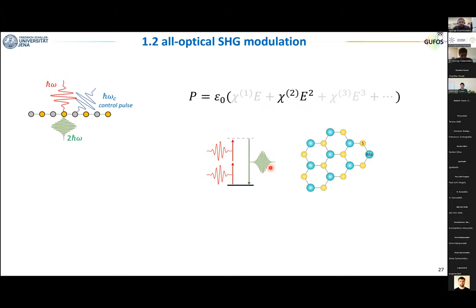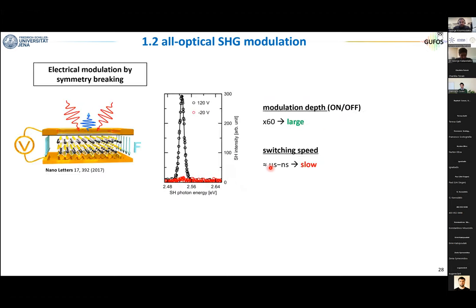Before I tell you what we did, maybe a brief state of the art. So when we started this project, there were already two main approaches to tune the nonlinearities in the transition metal dichalcogenides. The first one is the electrical modulation. Even here, there are different possibilities. The one that I like the most is the one that is based on breaking of space inversion symmetry. So now you can take a bilayer. Bilayer TMDs are centrosymmetric. You can now apply an out-of-plane electric field. And with this out-of-plane electric field, you break the symmetry.